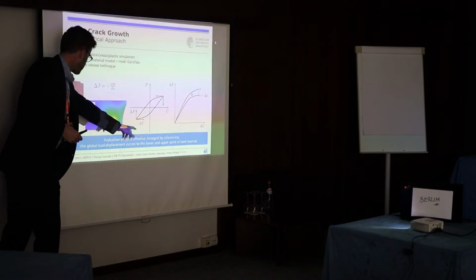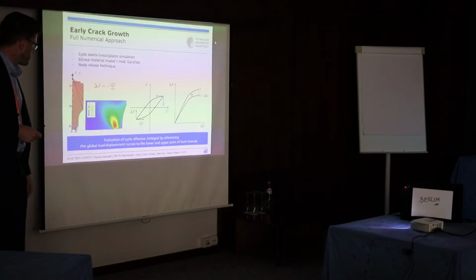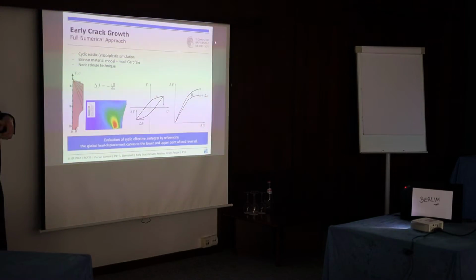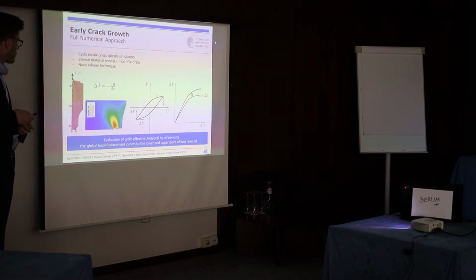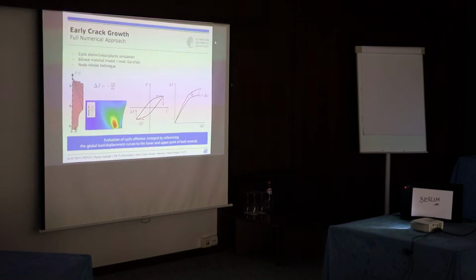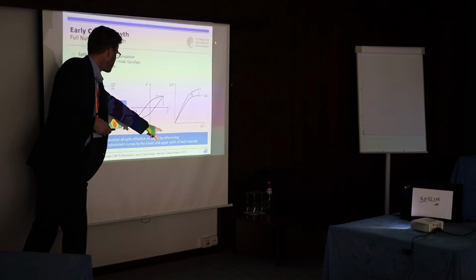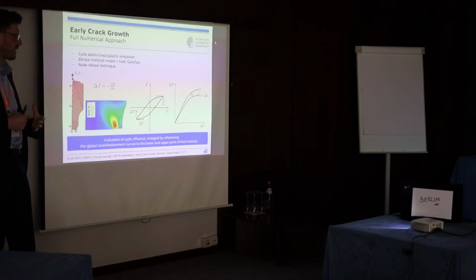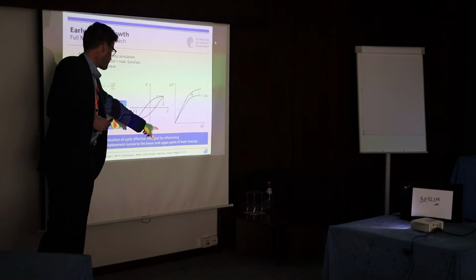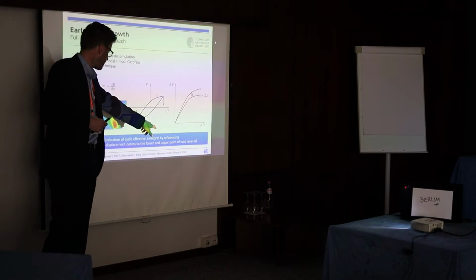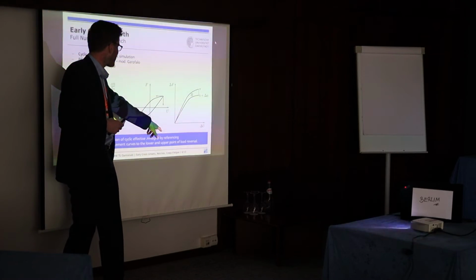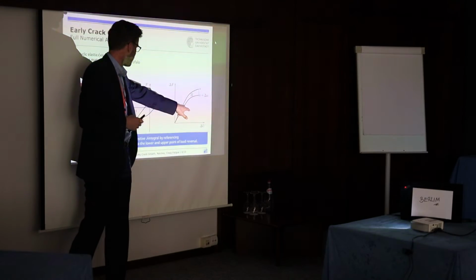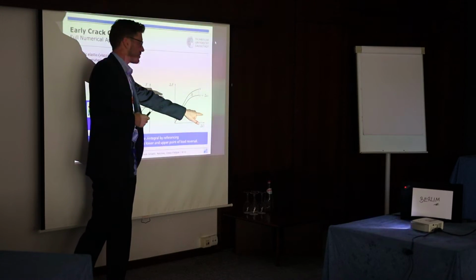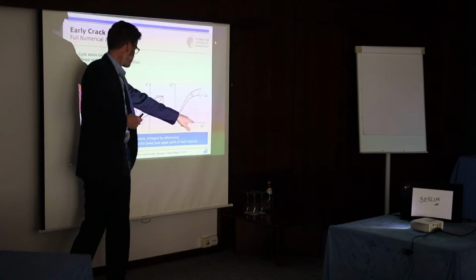You can see here the plastic wake. And this is important to do so to consider crack closure effects raised by plasticity or viscoplasticity. To determine now the crack tip loading, we use a cyclic J integral, and this is determined by the global force displacement curve, which you can see here in the middle. And to get a cyclic value of the J integral, we reference the global forces and displacements to the lower point of load reversal for determining the cyclic J integral for the upper loading branch. And we reference the values to the upper point of load reversal to get a value for the lower hysteresis branch.